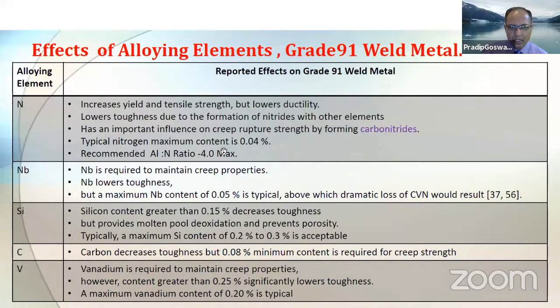First, start with the nitrogen. As you see in front of your screen, it has all good effects. In a way, it increases the tensile and mechanical strength, but has little effect on ductility. Lower toughness is due to the formation of nitrides and other elements. It has influence on the creep rupture strength by formation of carbonitrides. This is a very important aspect. This is a very important constituent with respect to the creep strength.